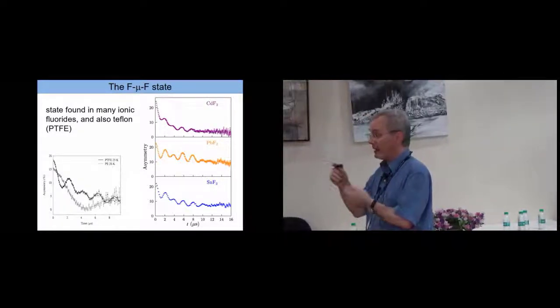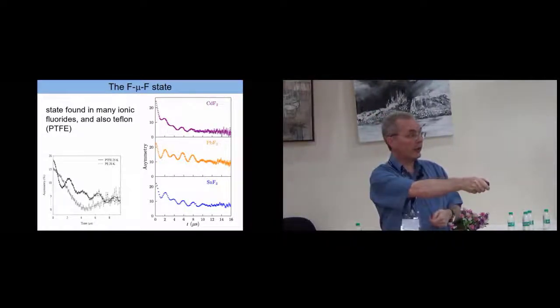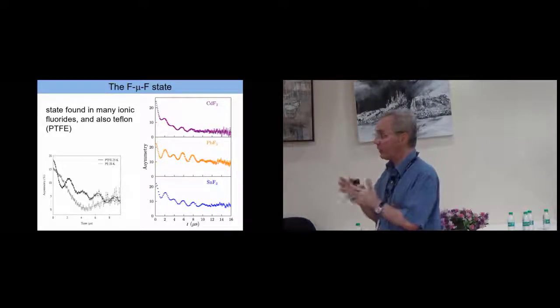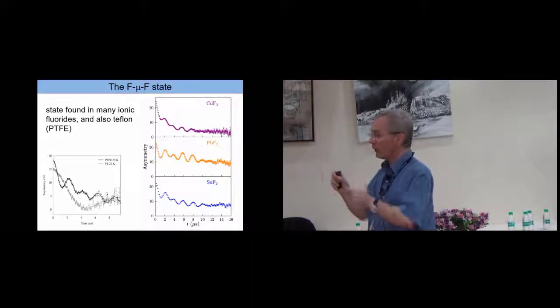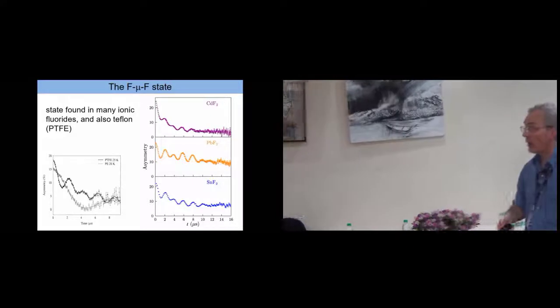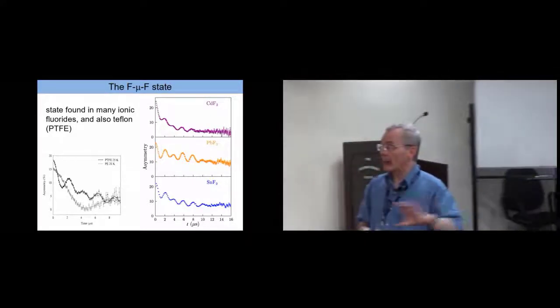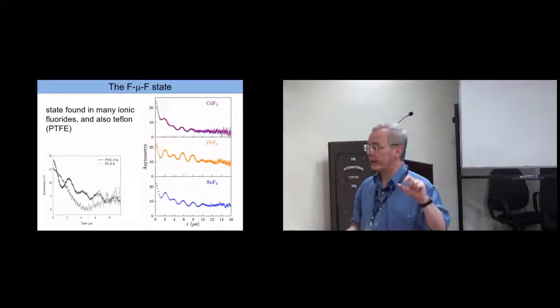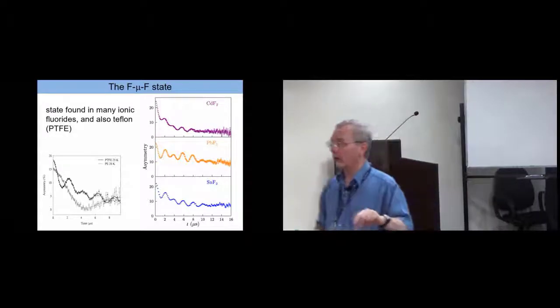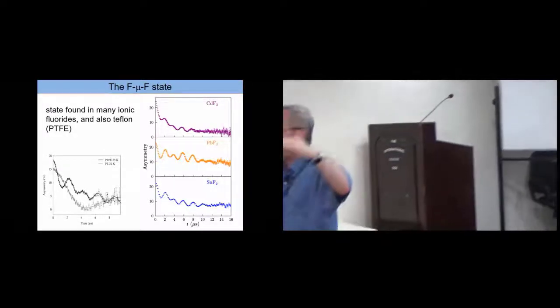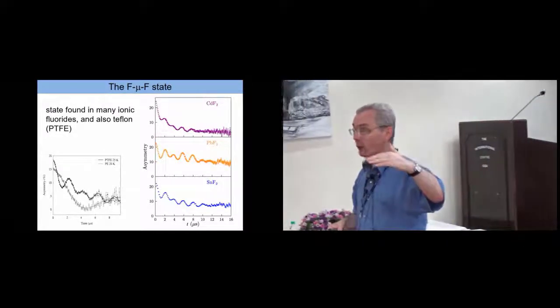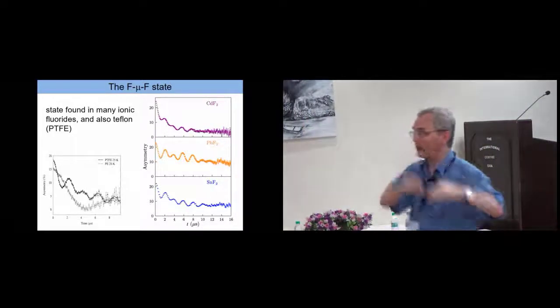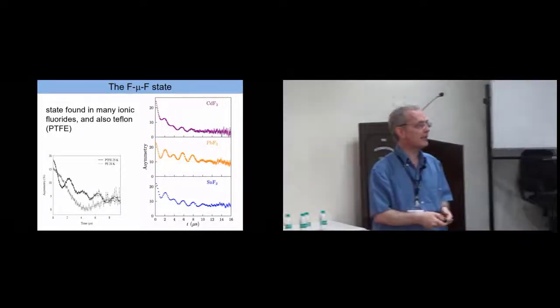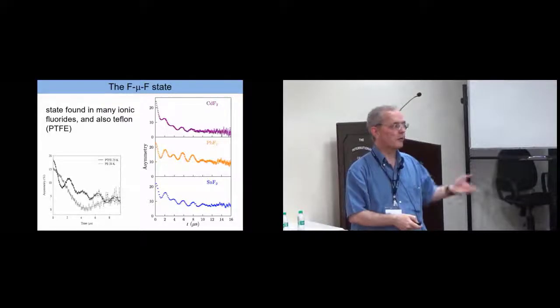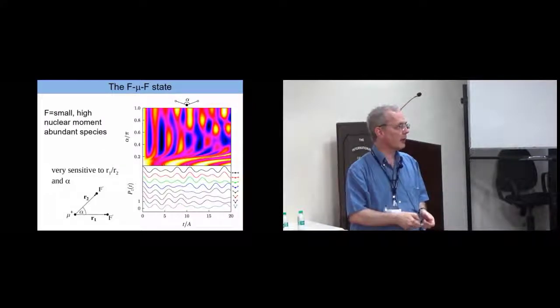But what you get from this is that the frequency of these oscillations gives you the distance between the muon and the fluorine. So in this case, you know the muon site. So in any material that has fluorine in, we can pretty well localize the muon. I think of the fluorine being a helicopter landing pad for a muon. You can attract the muon to this particular part on a complicated molecule. And we've done this now with a lot of molecular systems as well.